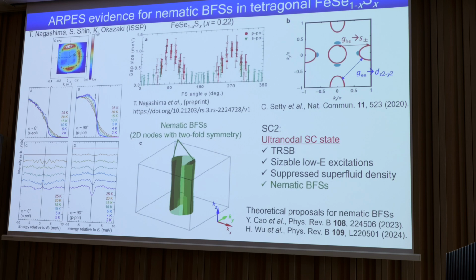I also asked our colleague in ISSP, Professor Okazaki, to measure laser ARPES in this SC2 region. They were able to map the superconducting gap as a function of Fermi surface angle, and found a strong anisotropy. There is an extended angle range in which the superconducting gap is actually zero. This is also consistent with the presence of Bogoliubov Fermi surfaces.